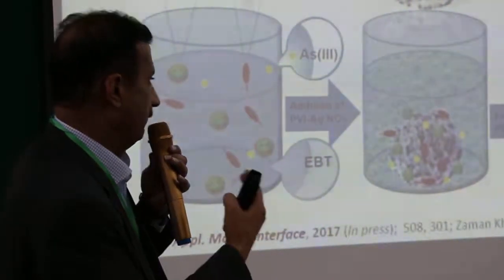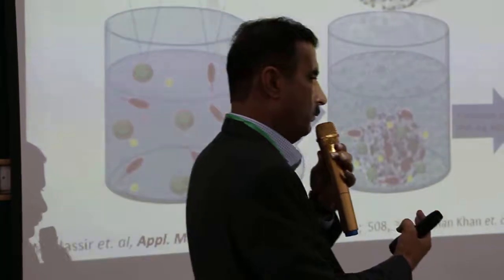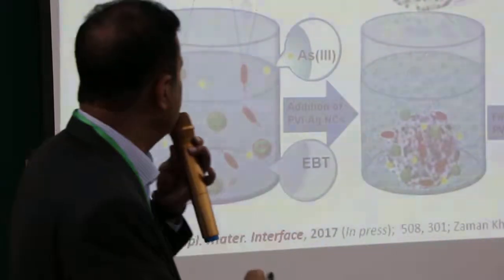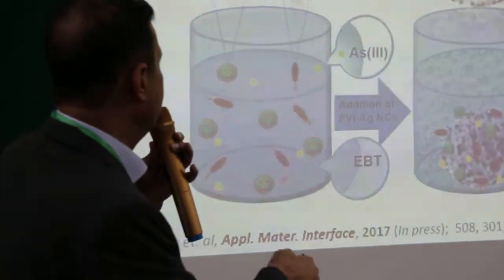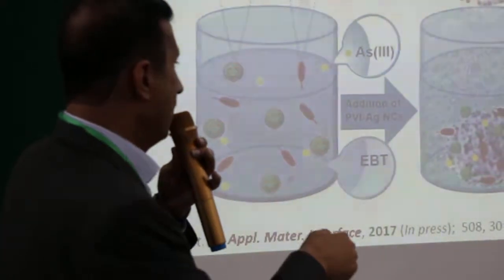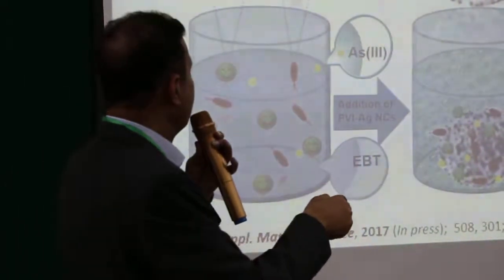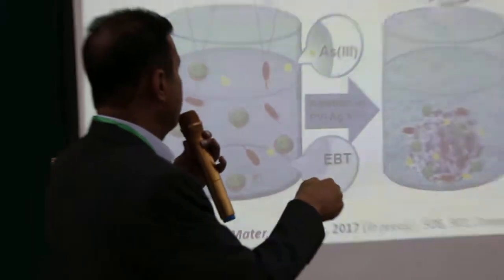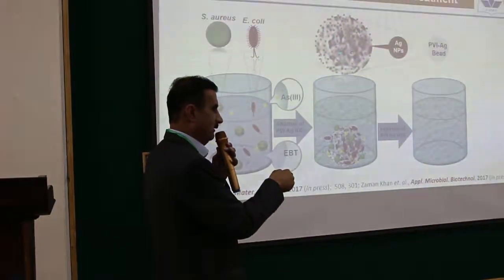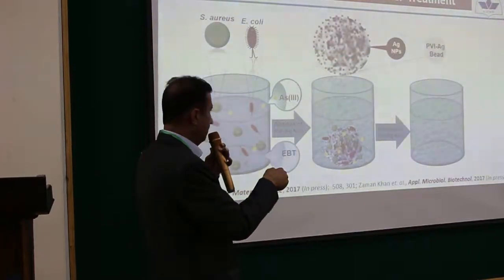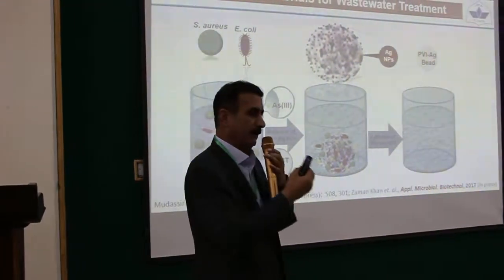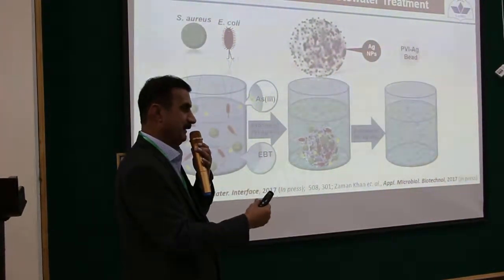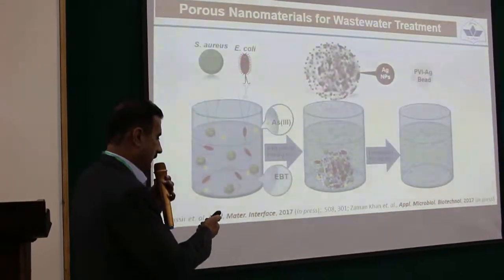We are working a lot on developing materials that can be used for the detection of different pollutants and simultaneously their removal. Here is an example where we developed hierarchically porous beads of particles with bigger pores, and within these bigger pores there are very small pores, and on the surface there are silver nanoparticles. They have a huge surface area and can be used to develop filters which can remove a variety of pollutants and even kill bacteria when water samples are passed through them.